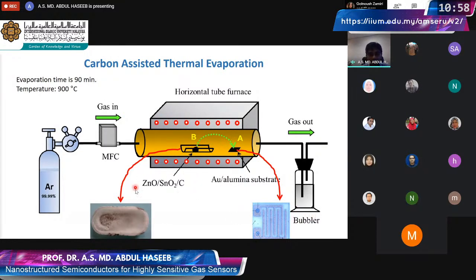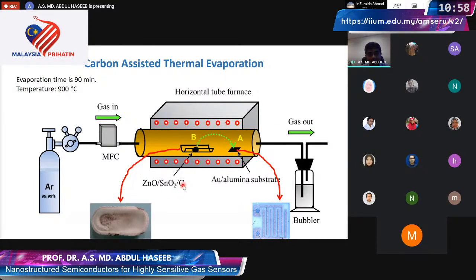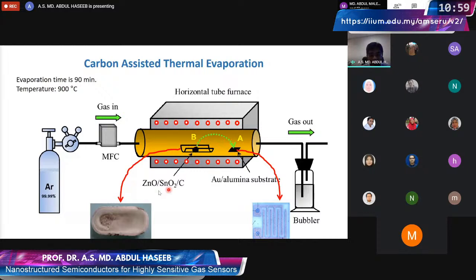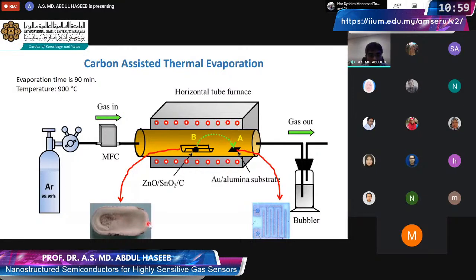Just to highlight the mechanism once again: we started with oxides of zinc and tin combined with carbon, and when we heat them at a high temperature, 900 degrees, this reaction happens spontaneously and zinc vapor will form. Zinc has a very high vapor pressure, and it will also take up some of the tin as vapor, and then it will shift. In this process, we did not make our system gas sealed, so oxygen leaked in. The oxygen is there in a small amount, and this whole metal vapor then comes to the surface and gets oxidized, and we have the growth of this oxide in the form of a nanowire. They also form on the surface of this boat as well. So they condense on the surface of the boat and form nanowires.